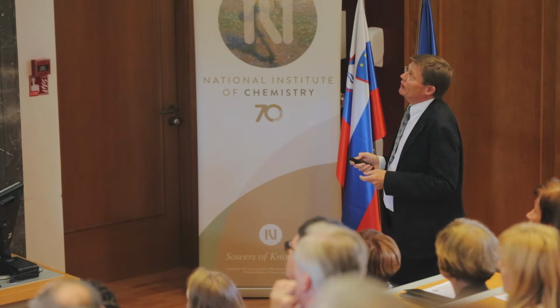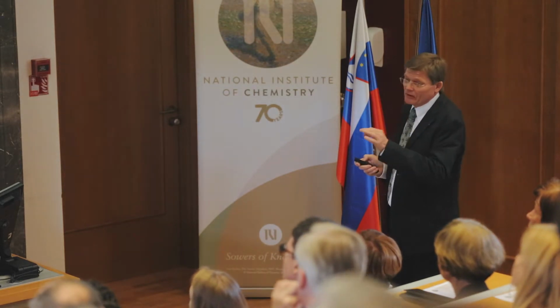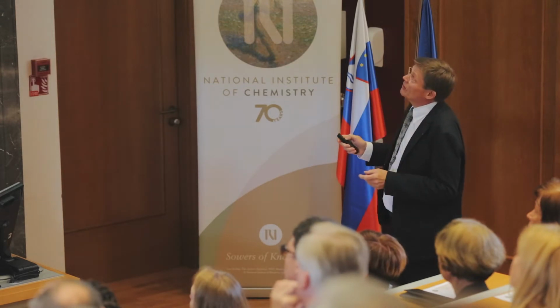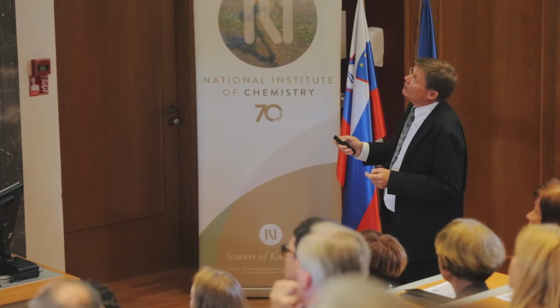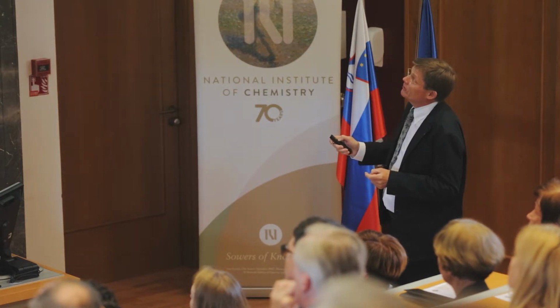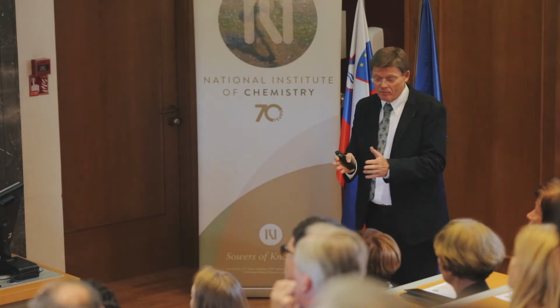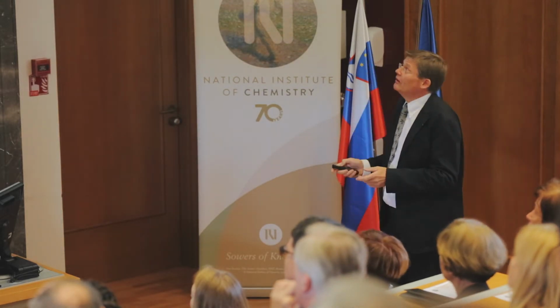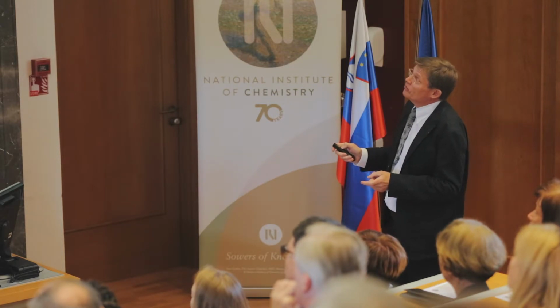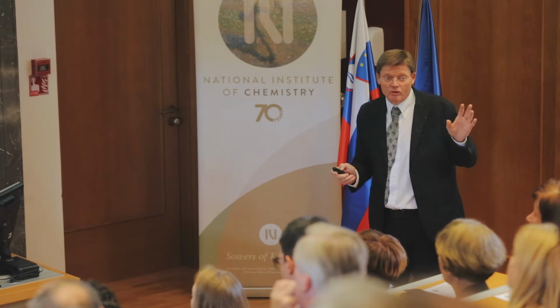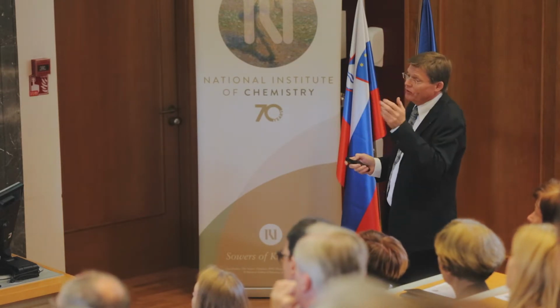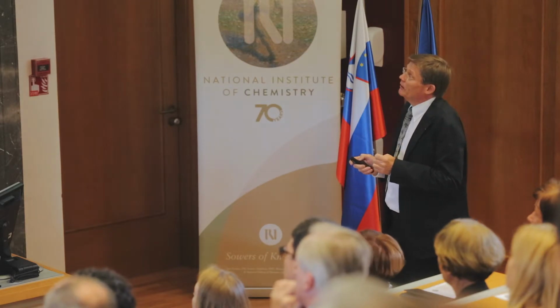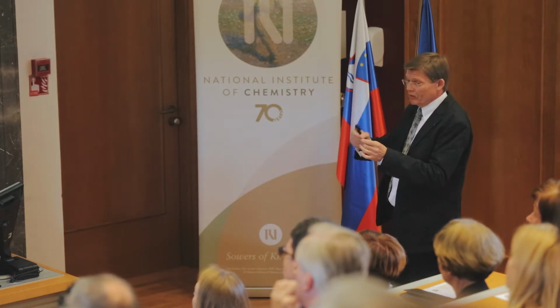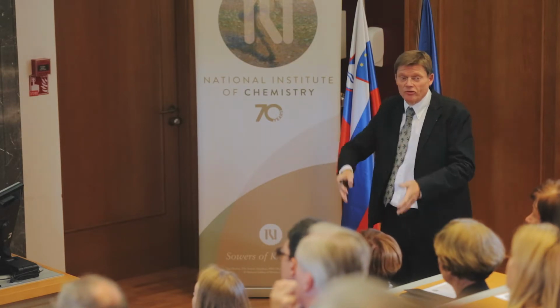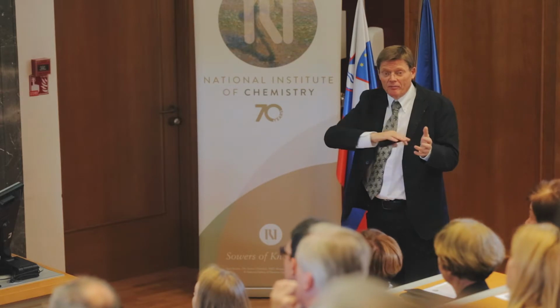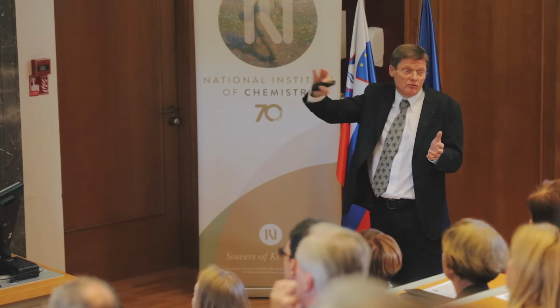So what was the first order understanding that we had in terms of these equivalent circuits? This is an equivalent circuit of such a sample. You have ions and electrons, the resistors. But usually you can't separate them. They appear together as a total resistor. And this is the dielectric capacitance. This may be standing for, let's say, internal grain boundary effects or interface. Now you switch on a current to such a system. The time dependence is typically then determined by the capacitance, not by the resistors. If you only had resistors, you directly get the result. The time dependency is certainly with capacitors.